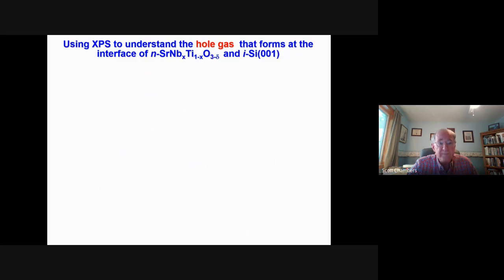All right, so let me then end with the research example. Now we're going to use XPS to try to understand this hole gas that forms at the interface between niobium-doped STO and intrinsic silicon. This was, by the way, a completely unexpected result. This was a baseline experiment. We didn't expect anything to happen.